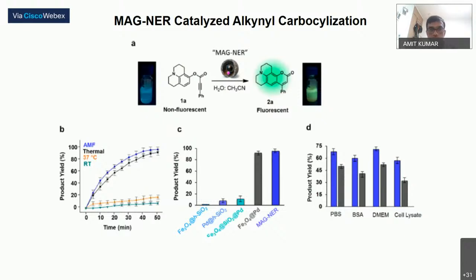So finally, we tested these magnetically operated nanoreactors for conversion of this kind of alkynyl substrate, alkynyl annulation, which is catalyzed by palladium. And in presence of AMF, the reaction completes within 1 hour. And by conducting control experiment only with iron oxide or palladium nanocrystals, it resulted in very poor yields. So the interface of palladium and magnetic core was very crucial for successful reaction.